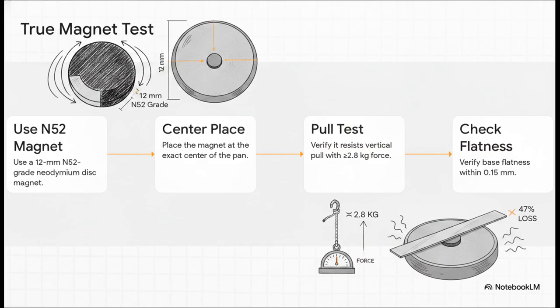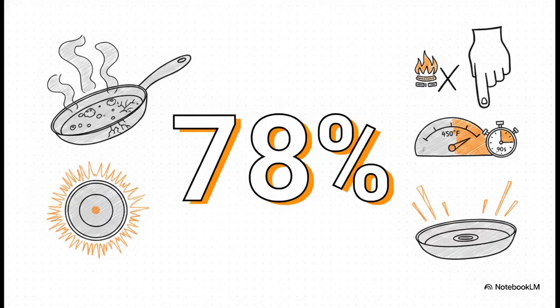Why go through all this trouble? Because a warped base reduces heating efficiency by up to 47%. That is a massive loss. And when we look at how this impacts everyday cooking, it turns out a shocking 78% of nonstick pans actually degrade faster on induction.